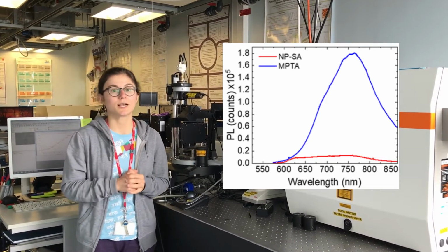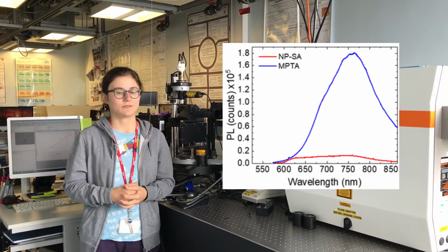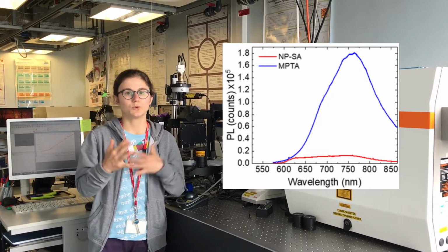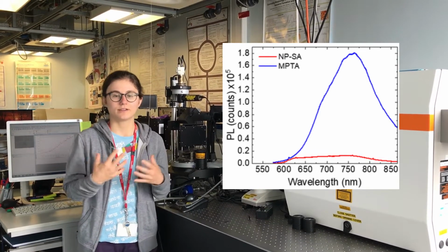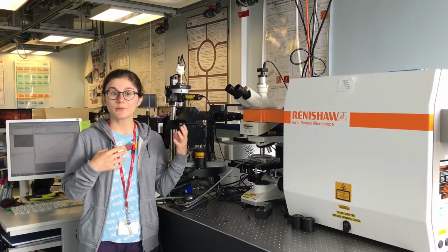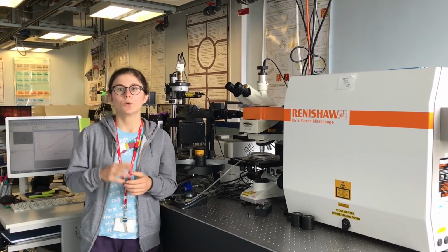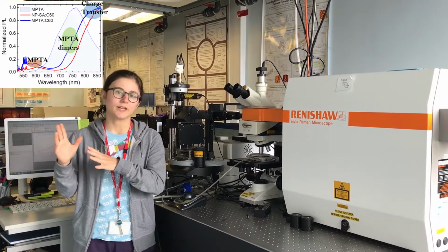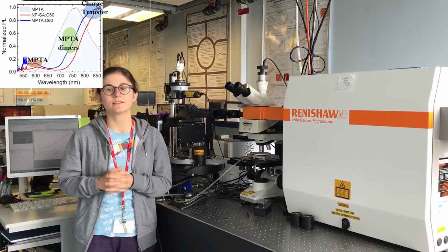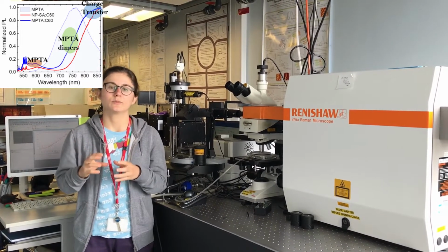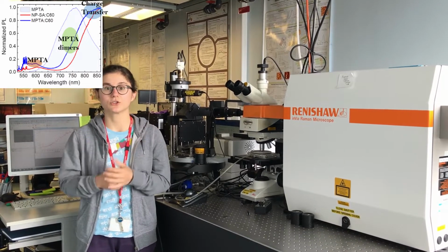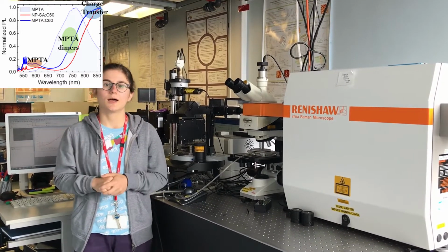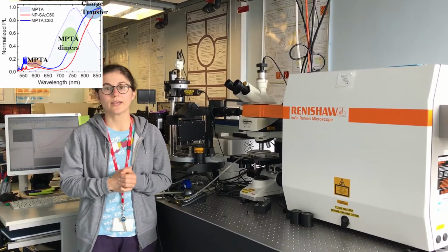In the neat material we have very broad and intense photoluminescence, which we attribute to intermolecular states, so very strong aggregation. And when we blend with the fullerene, we are basically destroying this aggregate, and we have dominant emission from the interfacial states, but we still preserve some degree of aggregation, so we still have some leftover emission from the aggregate.